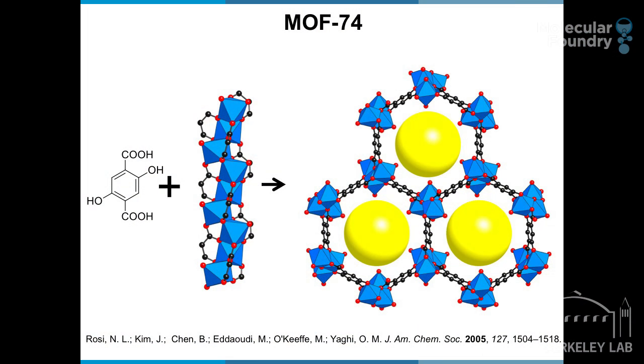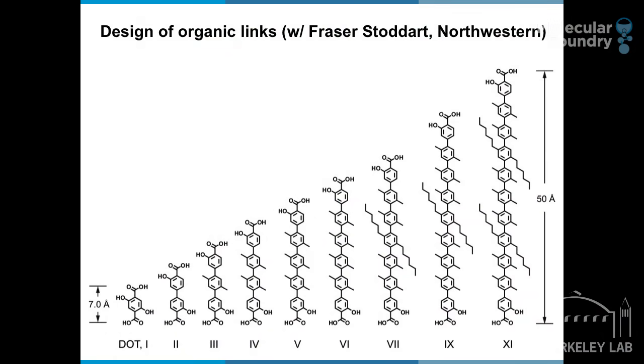Here we chose one member of the MOF family, which we reported in 2005, MOF 74. MOF 74 is very special because the multi-metal units are rod-like units that assemble in hexagonal form, linked by this simple organic unit. It's a special structure because no matter how long that organic link is, it will not interpenetrate, let's say self-grow, and therefore close the opening. So we set out, in collaboration with Fraser Stoddart, at the time at Northwestern, to use progressively longer links and test whether MOFs could be made.